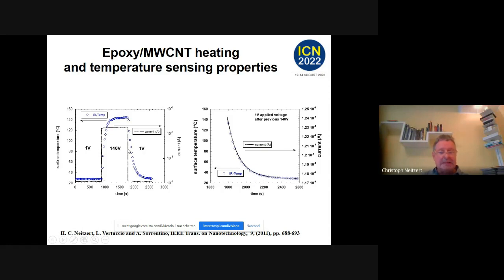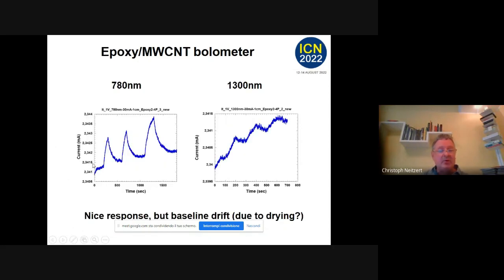It goes back to the same value, but now we use the properties, it's also almost linear, temperature dependent, but it's temperature and humidity dependent. Here you see the infrared temperature measured, and that is the current. It's linear actually. What if we use it as a bolometer? So we see again it's slow in some way because it's a very big sample. That's the only reason; here was the biggest sample from dimensions. We have a change in the baseline.